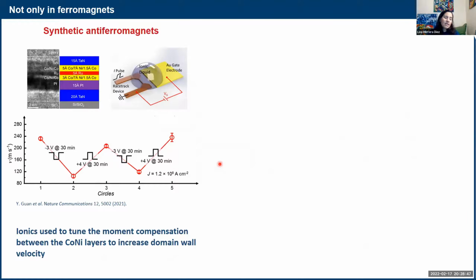Okay, so these effects are not only limited to ferromagnetic layers. We have seen in the literature, for example, this group use an ionic liquid to bias synthetic antiferromagnets. What is important to say about this study is that the same group, before this study, showed that magnetic domain walls can be moved at much larger velocities if the magnetic moment is compensated. So they grew a similar layer. They said, well, if we want to compensate the magnetic moment of the domain wall, then we just have to have something that mirrors the magnetic moment in the neighboring layer with an antiferromagnetic coupling.